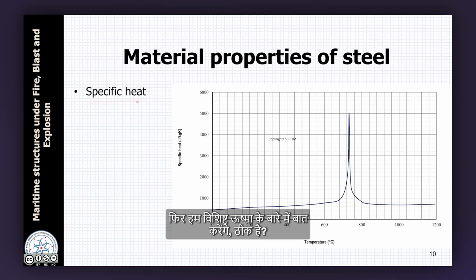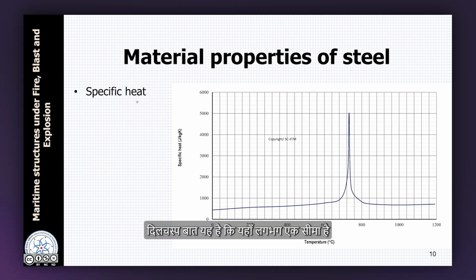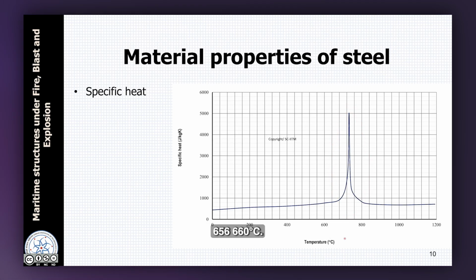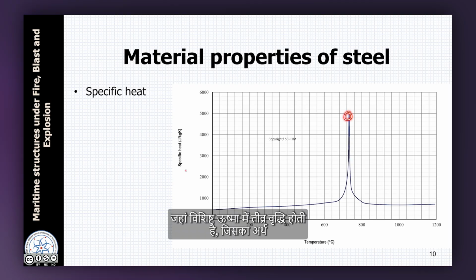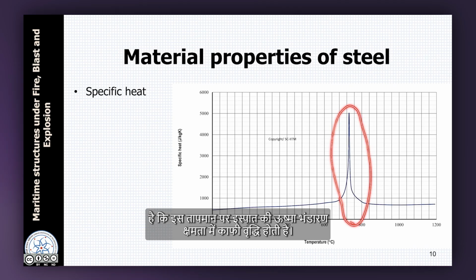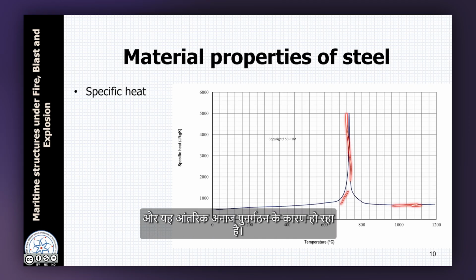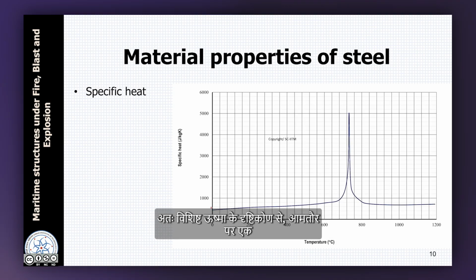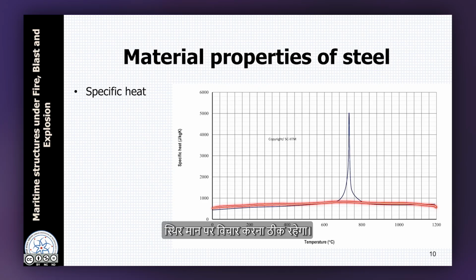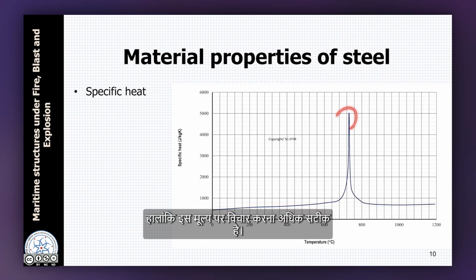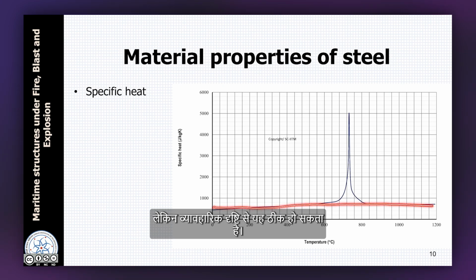Then we talk about specific heat. So, this is the variation of specific heat with respect to temperature. The interesting thing is that there is a range here around 650, 660 degrees Celsius, where there is a sharp peak in specific heat, which means that in this temperature, the heat storing capacity of steel increases substantially, but then again it comes back, and this is happening due to an internal grain restructuring. So, from a specific heat point of view, it would be generally okay to consider a constant value, although it is more accurate to consider this value, but for practical purposes this may be okay, it does not involve too much of an error.